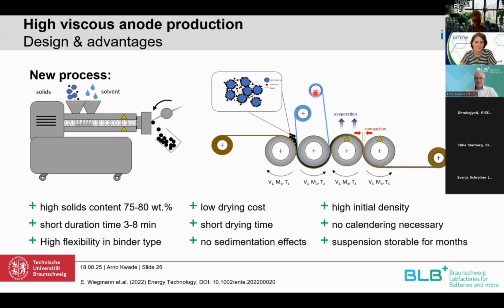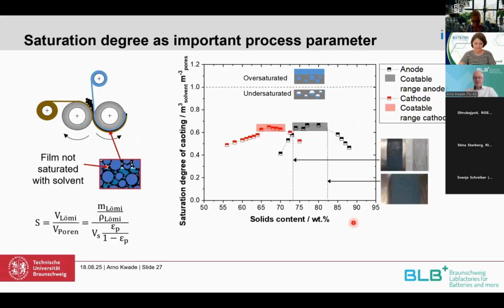In this case, we use a polymer foil to avoid high adhesion to the roller surface, and we have heated rollers, which is also typical for dry coating, so that we can dry the electrode just by heating it up this way. Then we also have a really short process, as we have seen for the dry coating. We have some drying costs, but they are really low compared to the typical normal process. We have short drying times and so on. No further calendering is necessary and so forth.